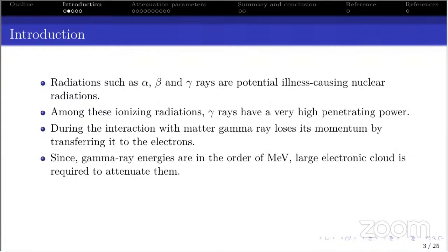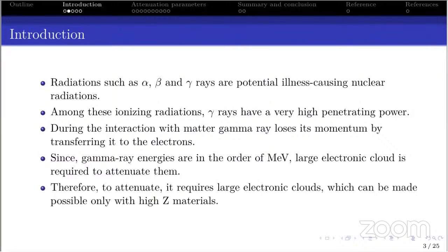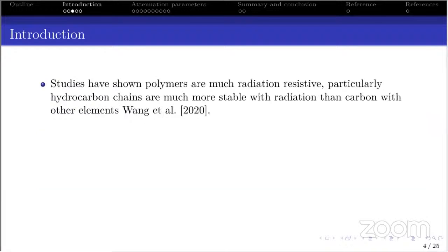We need a large electronic cloud in order to attenuate them, and in order to provide a large electronic cloud, we need a high-Z material. But the problem with high-Z material is that most of it is toxic. For example, the conventional material is lead. So we need to provide an alternative material to lead. In that direction, studies have shown that polymers are much more radiation resistive, particularly hydrocarbon chains, which are much more stable against radiation than carbon with other elements.